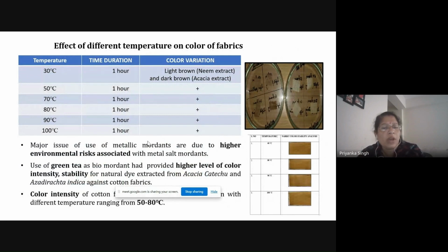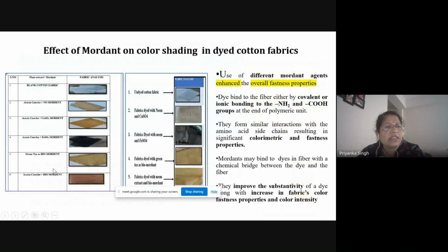So now, on the basis of the stability of this green tea, we have found a very good stability of this acacia catechu associated with green tea across the dyed fabric. This dyed fabric has shown very good stability compared to other biomordants. So we have selected this as the dyed cotton fabric for further study. A similar study we have obtained for the neem extract, so we have selected the neem extract with this biomordant and the acacia catechu with this biomordant for further study.